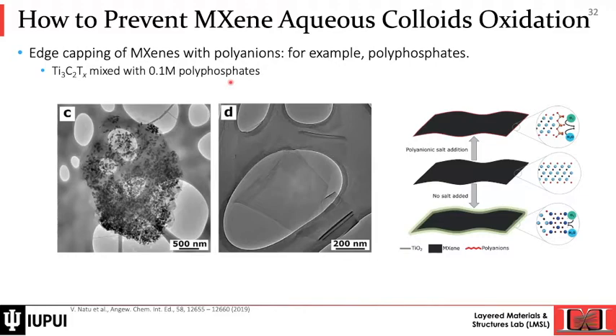They showed that these will just attach to the edges of MXene and stop the MXene oxidation. This is MXene after storage with edge capping and showed no oxidation.